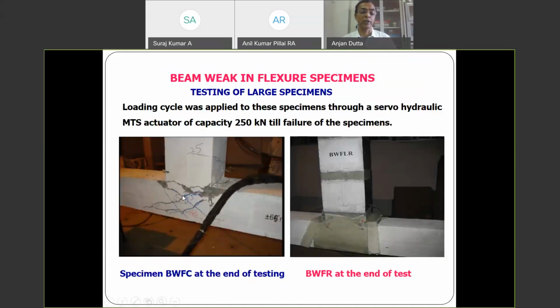Now, when you have tested your beam weak in flexure, you can see that there is a kind of hinge formation, because eventually it's a beam which is acted upon by load at the tip. So the maximum moment is at the support, and you see a hinge kind of formation. And then when we have retrofitted using FRP, you can see that finally, at the time of failure, the delamination is also taking place here.